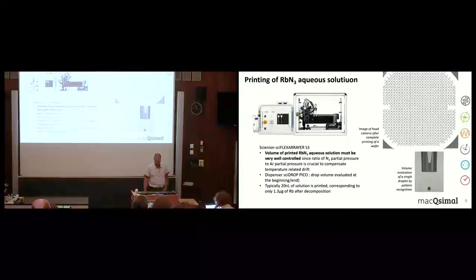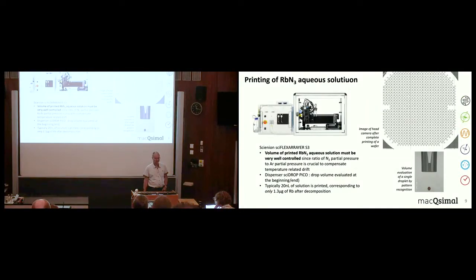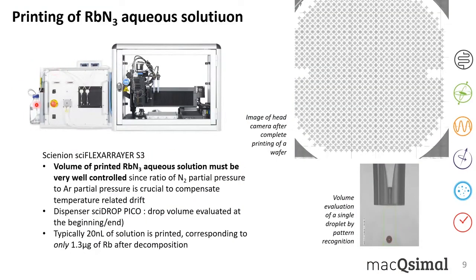Remember that I mentioned on one of the first slides that we make a UV decomposition of our rubidium azide that yields metallic rubidium and nitrogen. And since for the application, particularly in clocks, we have to have a very precise ratio of argon and nitrogen partial pressure, we have to very well control the quantity of rubidium azide that we put into the cell. And we found here a very nice instrument from the company Scienion in Germany, the sciFLEXARRAYER.